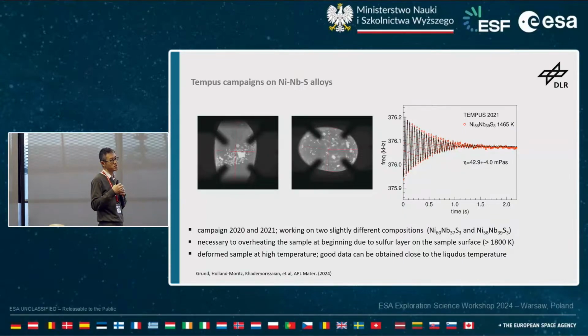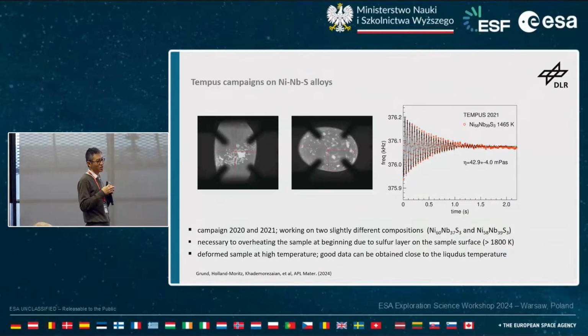So what you want is that the sample is damped solely due to its internal friction and not oscillating in a strange shape. And from there, you can then derive proper viscosity data. That's also the reason that the range we can assess in the parabolic flight is limited, because we need to wait longer after melting of the sample.